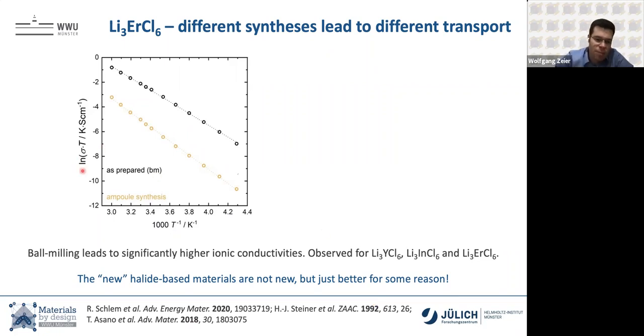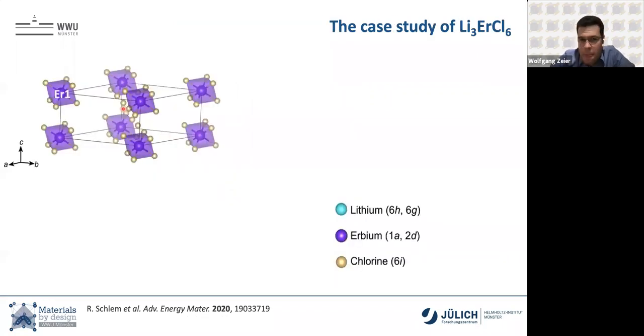So if you look at the logarithmic plot of ionic conductivity with temperature, this is the classically prepared materials back from the 90s. So in the end, you use your precursors, you stick them in an ampule, and you heat them up, and what comes out is a bad ionic conductor. If you ball mill the materials, just the precursors, no heat treatment, they're really good ionic conductors. Why? Well, let's look at the structure real quick.